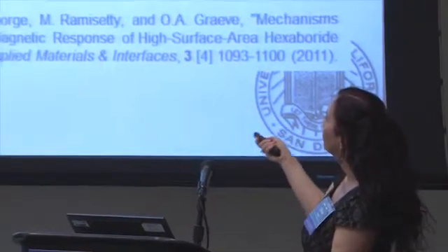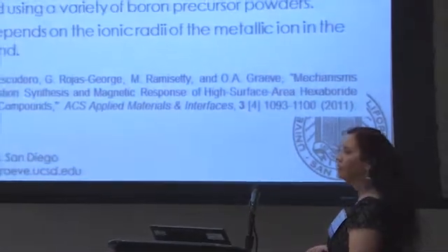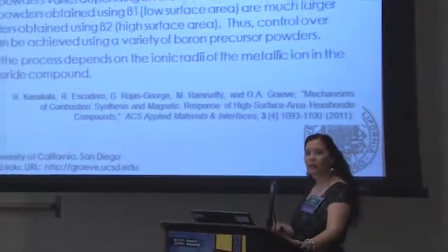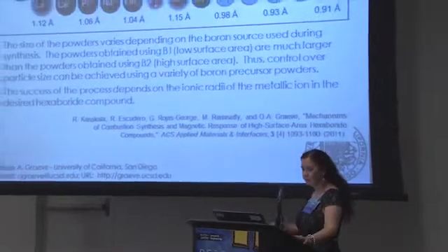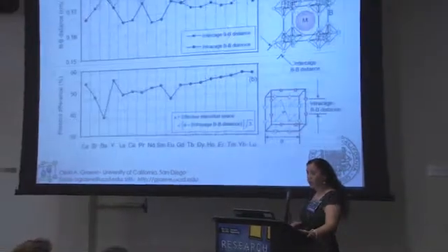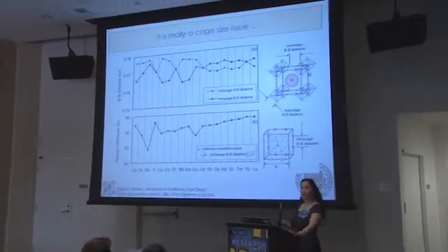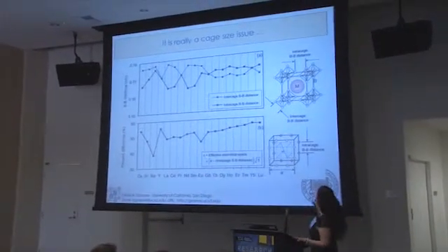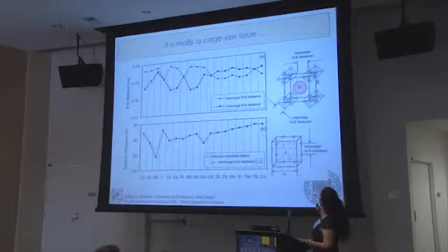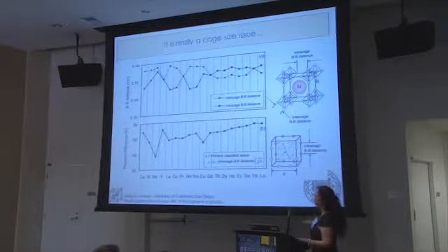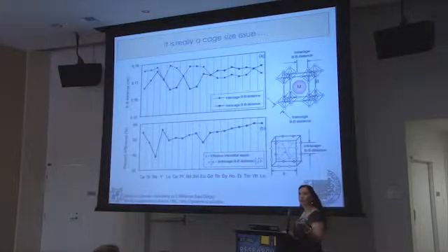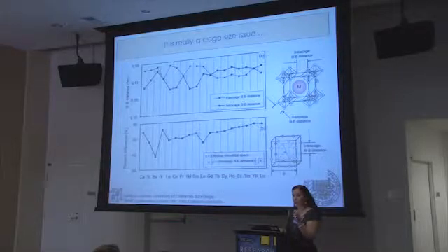These 2 are really quite small compared to the ones that you see, for example, right here, all of these. And so what is it about ionic size that prevents you from having stability in the system? It's actually not a size of the ion. It is a cage size issue. When you look at the crystal structure again that I had shown you previously, the boron framework in these materials is bonded by incredibly strong covalent bonds. And so this boron-boron bonding is really fixed in its length.